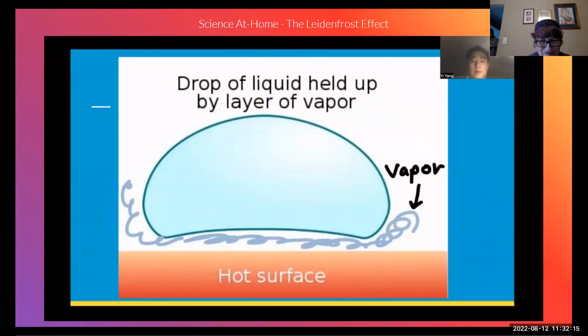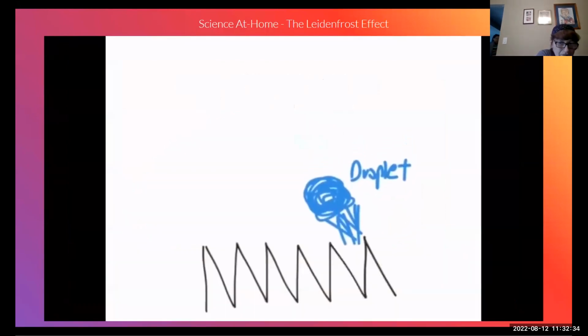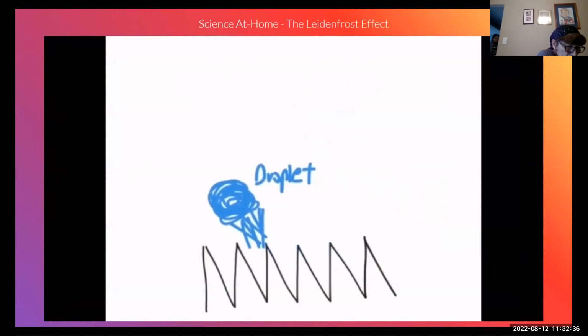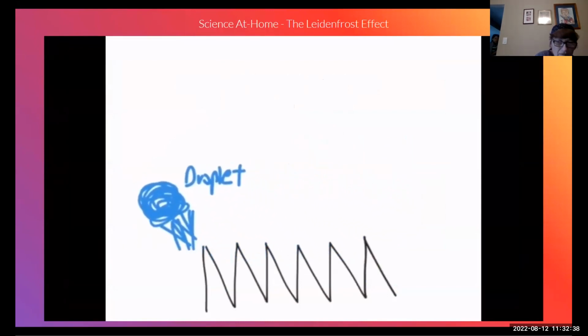Why do the water droplets levitate? When a drop is put on a really hot surface, the bottom part vaporizes so quickly that it creates vapor gas between the hot surface and the rest of the droplet, allowing the droplet to glide effortlessly around the pan. The vapor gas also helps the water droplets roll by itself on the other side of the pan. Each time hot vapor is produced, it acts like a small jetpack, pushing downwards and causing the droplets to roll.